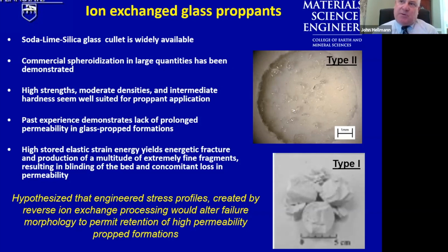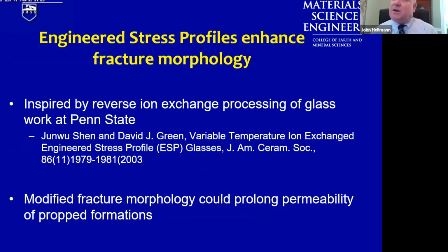So we hypothesized that we could modify the behavior of glass particles by engineering stress profiles in the proppant particles in such a way to make them fail into large chunks instead of fine particulates, and those large chunks would continue to prop. This work was inspired by things that were being done by my colleagues, Dave Green and Jun-Woo Shen at Penn State at the time, on engineered stress profiles in reverse ion exchange glasses. We thought that we could apply the knowledge that they were generating there to the development of a new class of proppants based on glasses, which would perform in an admirable way. And this would be done by modifying the fracture morphology and hence prolonging the permeability of prop formations.